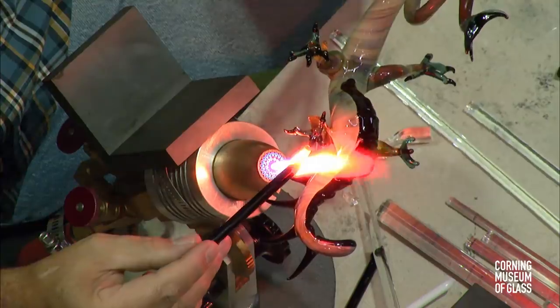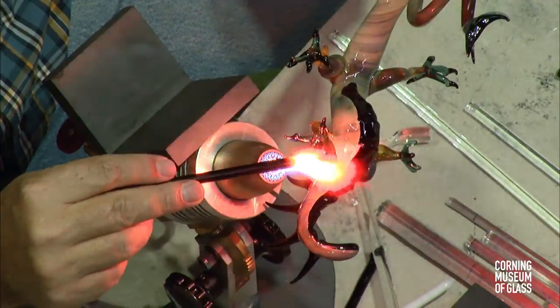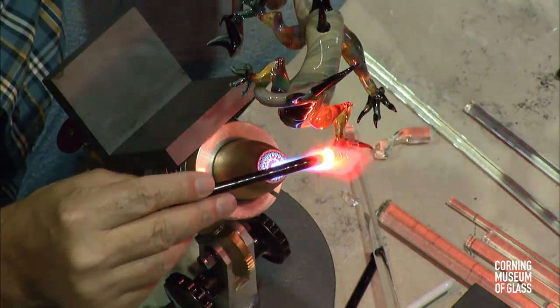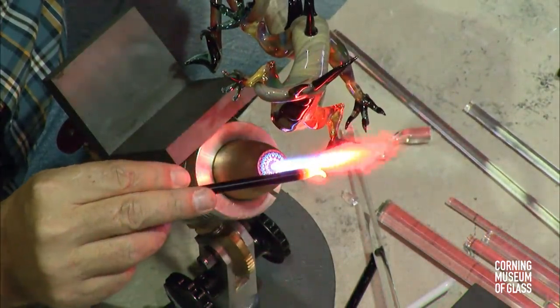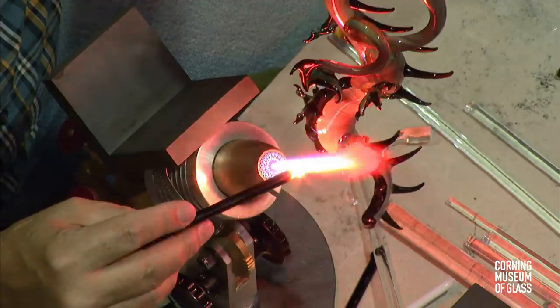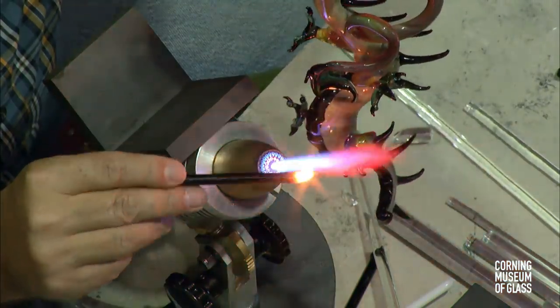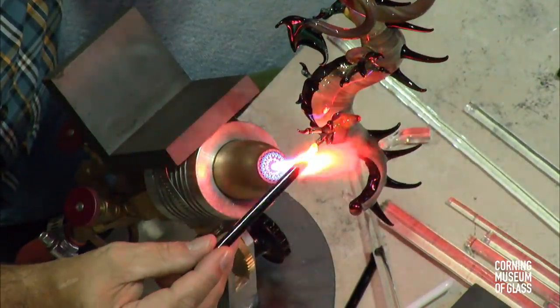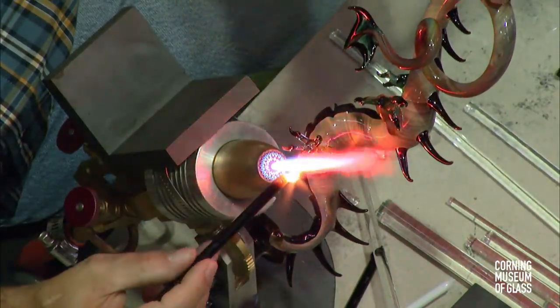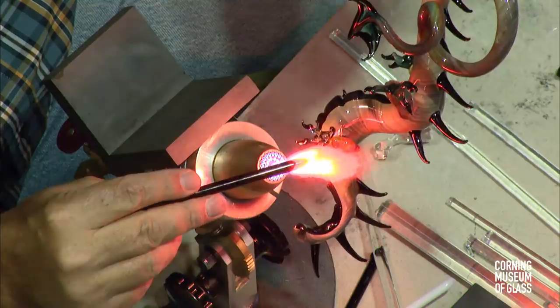Some of these different blacks work different ways. Some of them are softer, some are stiffer at the same temperature. So there are different preferences for different blacks for different purposes. If you want a certain density of black, maybe you're pulling something very thin, I might use Eclipse Black or a Raven Black, which tend to be more dense, so if I pull them very thin, it still holds that nice black color. This Jet Black, if I'm sculpting with it, is really handy. It's very soft, so it flows easily and quickly. But if I thin it out too much, it looks blue, so that's a consideration there.